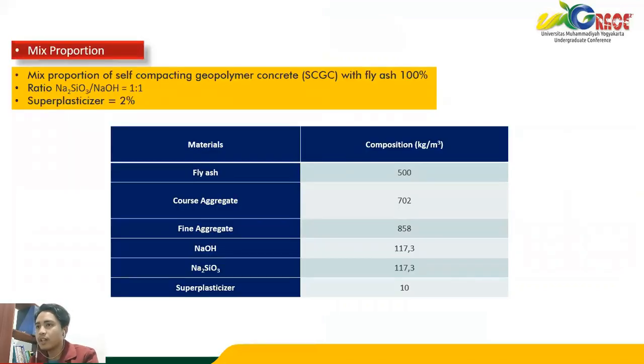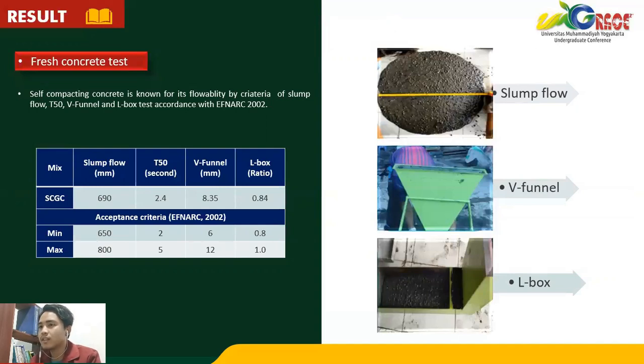This is the mixed proportion. The mixed proportion of the self-compacting geopolymer concrete is fly ash 100% and a ratio of natrium silicate to natrium hydroxide of 1:1, with superplasticizer only 2% of the precursor. So the result, the first, fresh concrete test: we can see the pictures of slump flow, V-funnel, and L-box. We get the data, and all of the tests met the acceptance criteria by EFNARC 2002.